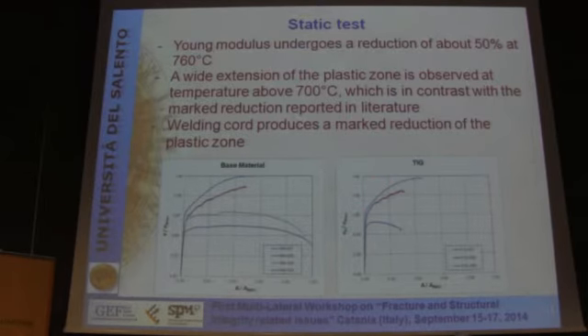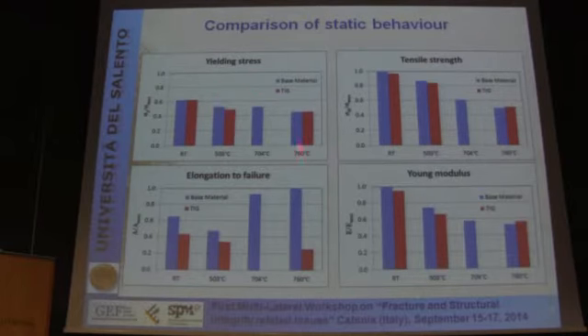In fact, if we compare yield stress, tensile strength, and Young's modulus, the effect of the welding bead is practically negligible, while elongation to failure is dramatically reduced, especially at the highest temperature.